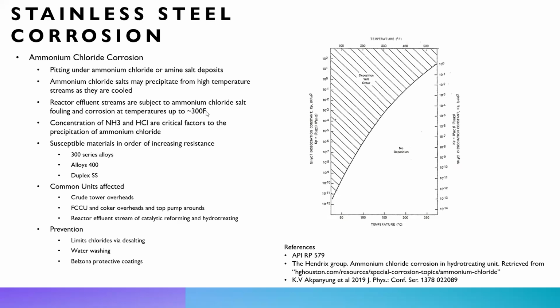So something that we could help with, which is a pretty common corrosion phenomenon, is ammonium chloride corrosion. So this is when you have pitting under ammonium chloride or amine salt deposits. The ammonium chloride salts can precipitate and they form deposits on your substrate, and then you'll get pitting corrosion underneath it. So all of your stainless steels can be susceptible to this, especially your 300 series alloys. As you increase up to the alloys of the 400 and the duplex, you're going to increase the resistance to this, but you still could have some problems.